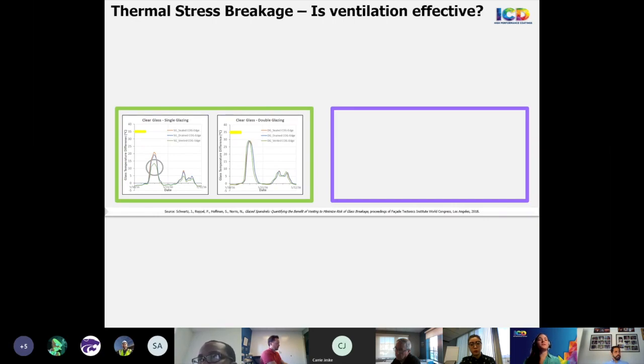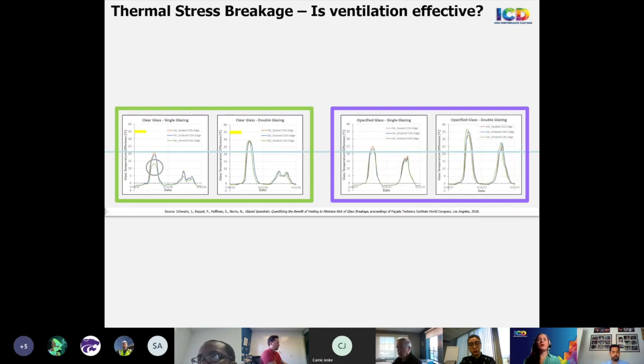And with insulated units, there's not much of a difference between the three options, and we're just starting to reach the level of danger of thermal stress breakage. Now comparing against the opacified results, looking at the condition for monolithic, the temperatures increase but are still below that 35-degree critical range. But for IGU, you can see they now start to reach out of that range. So there's a risk that can be dealt with by heat strengthening the glass, but adding a ceramic frit can take away some of that benefit, as we saw in Kayla's presentation, and I'll be showing a coating alternative in the next few slides.